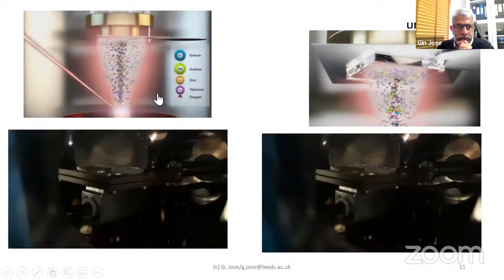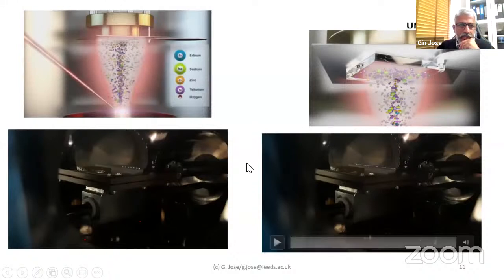So here is a simple example of how it happens in real time. You have a laser interacting with the material, creating ions and nanoparticles of the target material, which get deposited on the substrate. That's what we call pulsed laser deposition. The process I described here is slightly different from the first part of the talk, in which the deposited materials are diffused or doped into the glass, so that you essentially change the composition of the substrate with the incoming material ablated using this femtosecond laser.